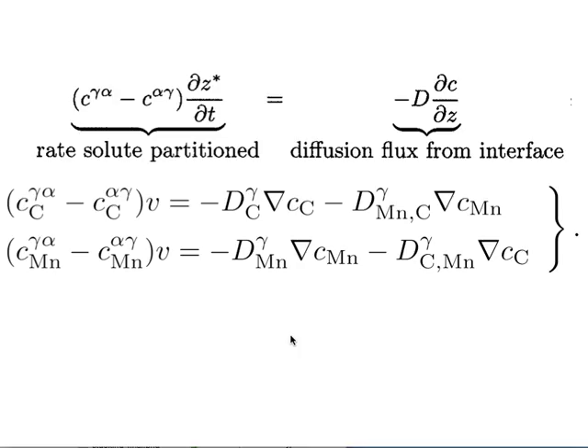So, in the binary case, we obtain the necessary equations by looking at the rate at which solute is partitioned and the rate at which it's carried away from the interface by diffusion in order to maintain the equilibrium concentrations at the interface. All right, those two terms must be equal. For the ternary case, we have greater complexity. First of all, we have two equations. V is the velocity, and there's only one interface moving, so the velocity is the same in both of those equations here. These are the equilibrium concentrations of ferrite and austenite with respect to carbon and with respect to manganese.